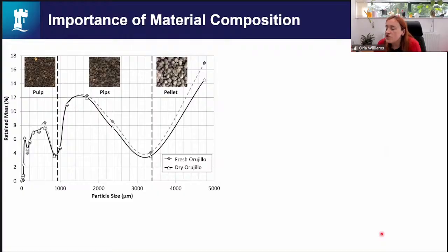When we looked at the composition, the particle size distribution of the olive waste, you can see it's composed of three parts. We have these agglomerations and pips and pellets above 3.35 millimeters. We then have this midsection, which is the pips or the olive stones, because if you think about an olive, it has a stone and then an outer fleshy layer. That fleshy layer is the pulp, which comes below 1 millimeter, so this is fine material. So you have three different parts to the material, and we wanted to see what was happening with each of them.